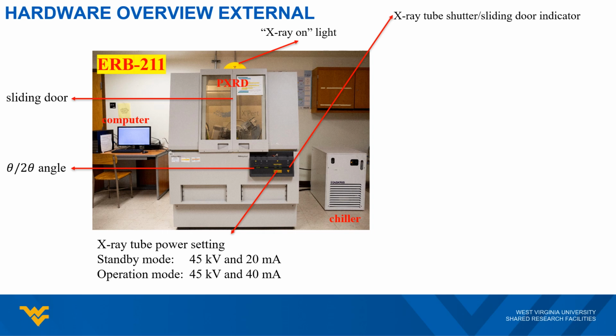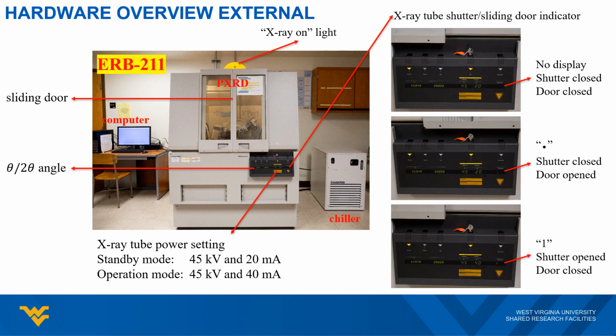The X-ray tube power setting should be either 45 kV 20 milliamps in standby mode or 45 kV 40 milliamps during the measurement. For the shutter and sliding door indicator, it should be either no display, which means both the shutter and the door are closed, or a small dot, which indicates the shutter is closed while the door is open. This will allow you to install samples and modify X-ray optics before the measurement.